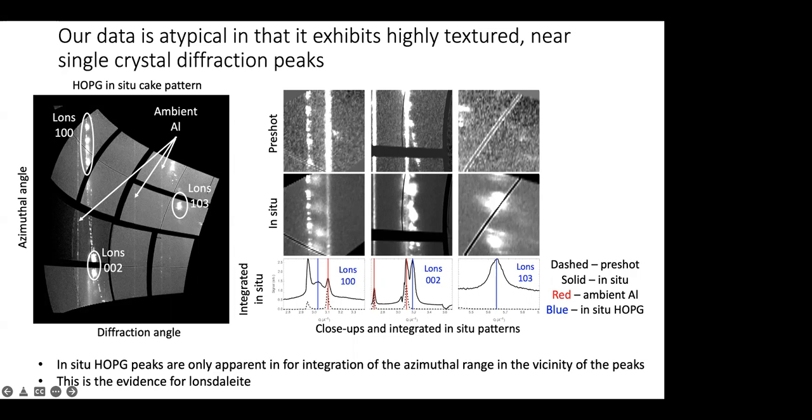So what that indicates is that these samples are very highly textured, very highly oriented, and that the product is very likely strongly oriented with respect to the initial state. And this implicitly confirms a speculation by Nellis years ago when they did their shots on graphite, that this is a martensitic transformation. This does seem very consistent with a diffusionless transformation.